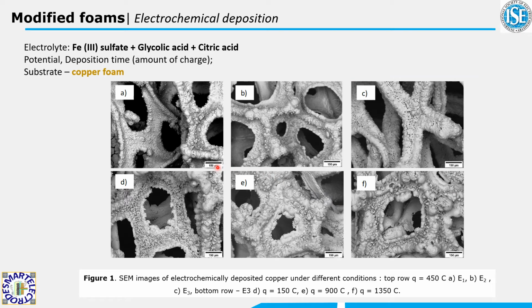Trying to increase the activity of classical Fenton's reaction, we have electrochemically deposited iron on copper foams using an environmentally friendly electrolyte consisting of iron(III) sulfate, glycolic acid, and citric acid. We investigated the morphology of foam deposits using scanning electron microscope images, which you can see in the first figure. We have investigated the effects that deposition potential and deposition time have on the morphology of the deposits. Deposition time was controlled by varying the amount of charge that was passed through the cell.